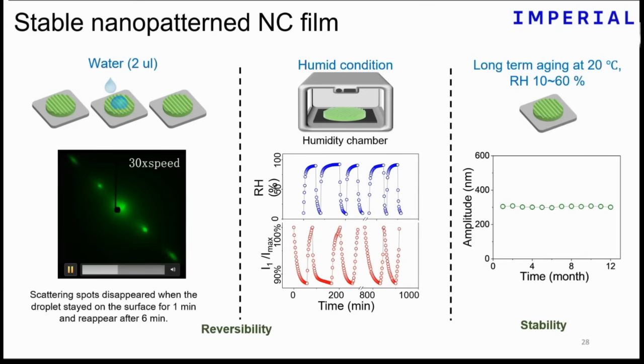She's taken this through hundreds of humidity cycles, and the pattern responds to humidity because cellulose is hygroscopic, but it always seems to bounce back and recover. And over many months, over a whole year, they have stayed.